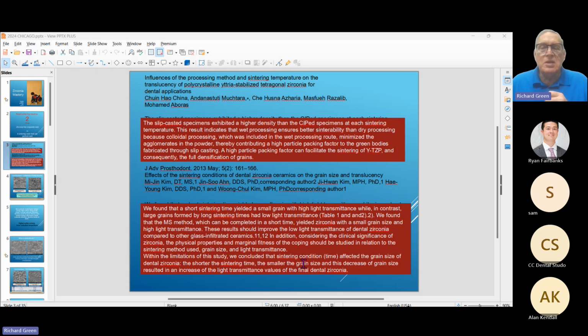In this bottom study, it talked about the fact that we concluded the sintering condition, that is time, affected the grain size of dental zirconia. The shorter the sintering time, the smaller the grain size, and the decrease in grain size resulted in an increase in light transmission values of the final dental zirconia. So what they're saying is that small grains, lower sintering temperatures, shorter times, all of these things work really well if you have a zirconia that has fine grains. That is what you're looking for.